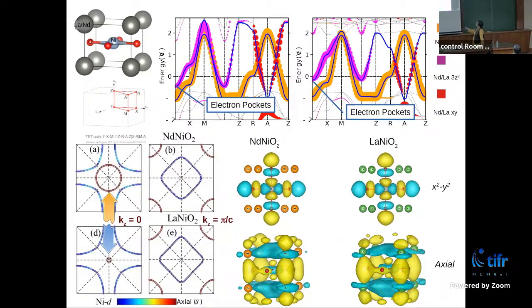And in contrast to neodymium, in the case of lanthanum you see this pocket just shrinks and almost disappears at the gamma point. If you make a Wannier function description, you see the x square minus y square Wannier function is more like the cuprates, except it is far more localized. If I had shown you the corresponding plot of the Wannier function for the cuprate, it would be really spread out. It goes to fourth, fifth, sixth nearest neighbor and connects to all different oxygens. Here, it's only to the nearest neighbor oxygen.